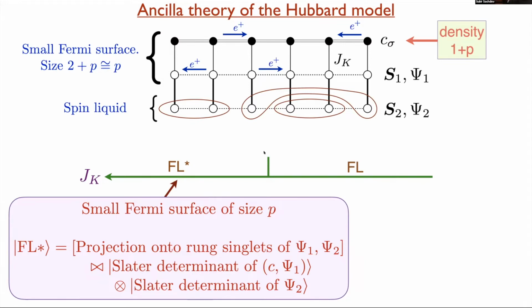We're adding these two layers, but in a way that we know how to work with using field theory and other tricks. But in the end, when you do this projection, there's no dependence on the left-hand side. This state is a function only of the coordinates in this physical layer. And we know how to do that with gauge theories in higher dimensions. There's some similarity to ideas of tensor networks, but tensor networks don't have fermions to begin with. They can't even get a Fermi surface, and everything has to be done numerically. Here we have some ideas on how to proceed with this kind of ancilla degrees of freedom.